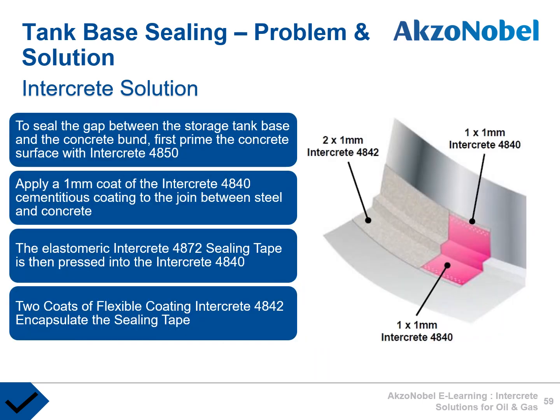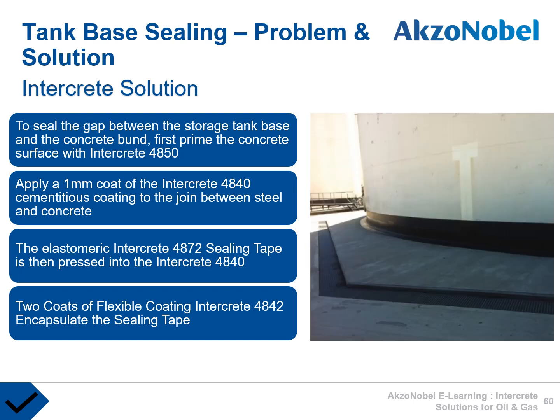And the Intercrete solution, to seal the gap between the storage tank base and the concrete bund: first of all, we prepare the steel and concrete with UHP, and then we prime the concrete using Intercrete 4850, which is a primer. We apply a 1 millimeter coat of Intercrete 4840 cementitious coating to the join between the steel and concrete. The elastomeric Intercrete 4872 is a sealing tape, which is then pressed into the Intercrete 4840, and the final application, 2 coats of the flexible coating 4842, encapsulate the sealing tape. And there is an example of the system as completed.